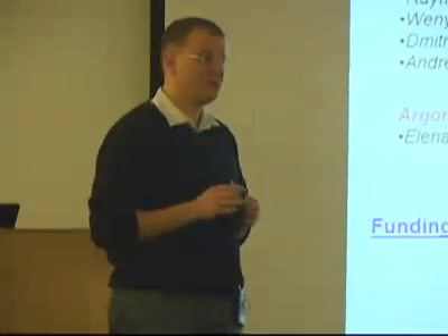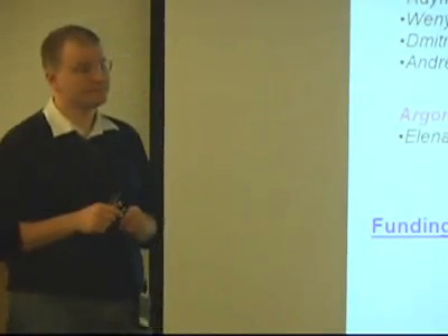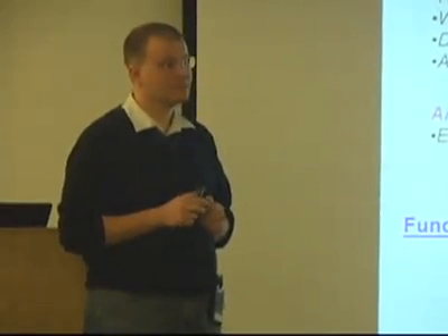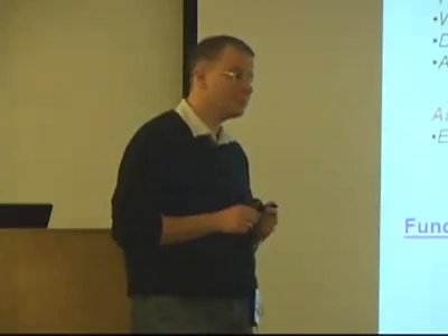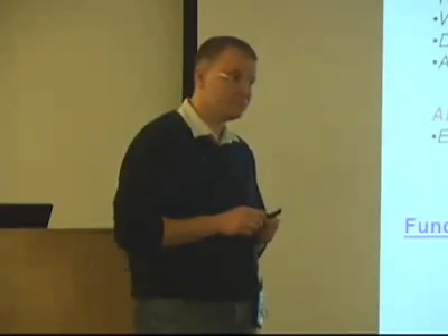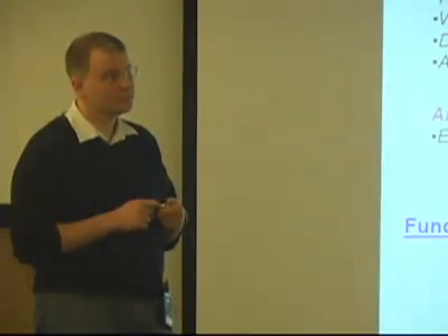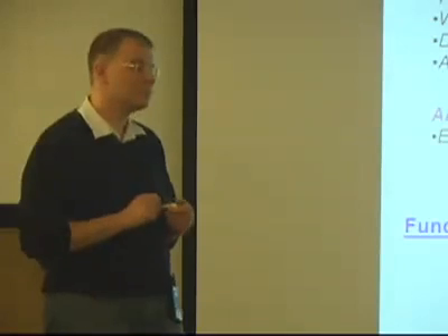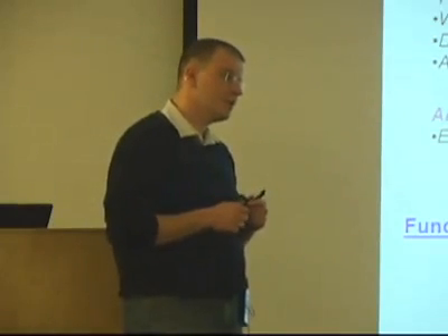Your comment is correct. I mean, it's not a perfect single crystal. You have some states, but the states we found are very shallow. The steady-state photoconductivity is usually temperature independent, even in this disordered system. The peak transient photoconductivity, steady state in this case, is on the order of an activation energy of 3 millielectronvolts. So it's pretty mild. And what did you see in terms of dark conductivity?